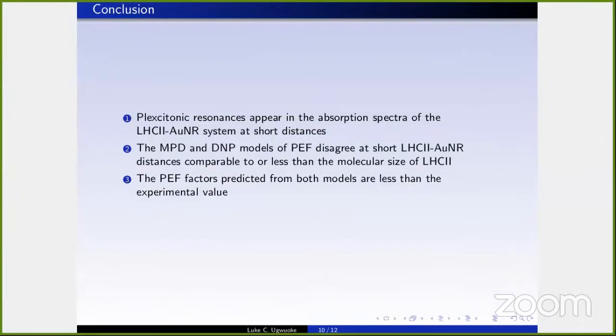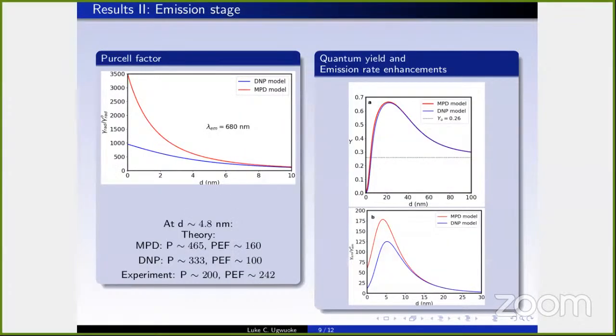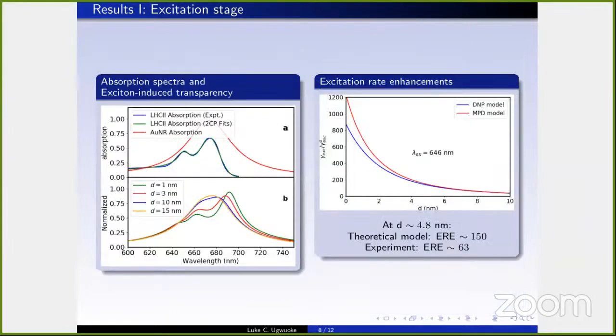Yeah, so it can be an enhancer or an inhibitor, depending on how close you are to the nanoparticle surface. And this is why in the lab, they usually coat the surface with some dielectric, because if the fluorophore interacts directly with the metal surface, it can lead to surface-induced quenching of fluorescence. So that distance is always a problem in the lab. Experimentalists always battle to control that distance to find an optimal distance for the enhancements to take place.